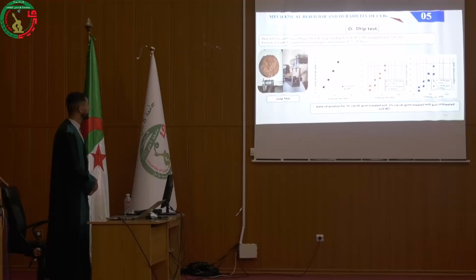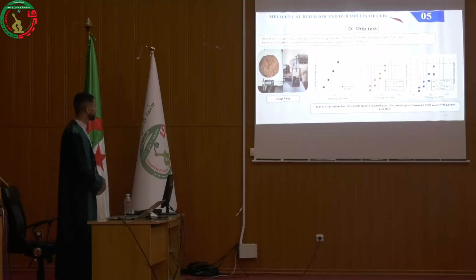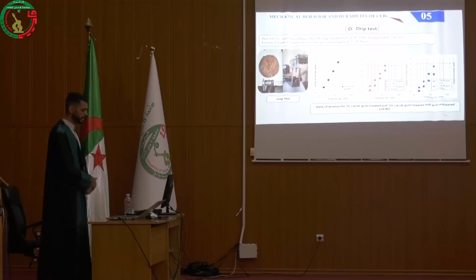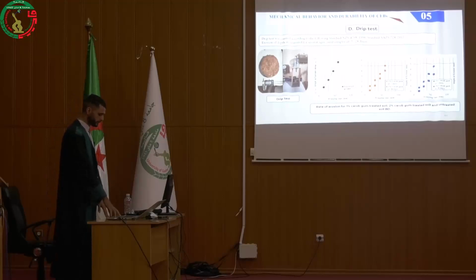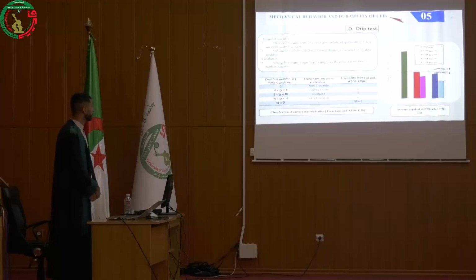We arrive at the durability of the CEB. The drip test was carried out according to the following standards. Depth of erosion is measured for several ages of cured samples: 0, 7, and 28 days. The depth of erosion is measured every 15 minutes. In the erosion test, the untreated specimen and the 1% carob gum stabilized specimen at 7 days and earlier are prone to erosion. Specimens with less than 5 mm erosion depth are classified as slightly erodible.